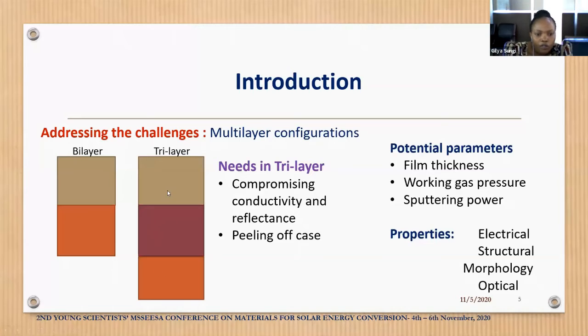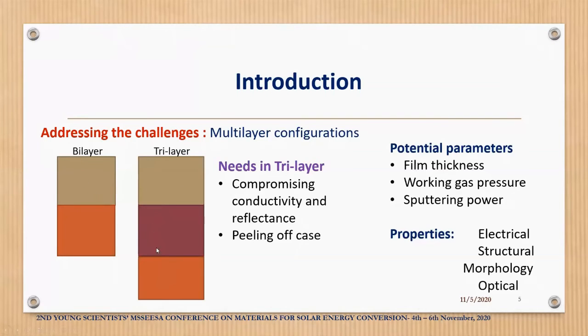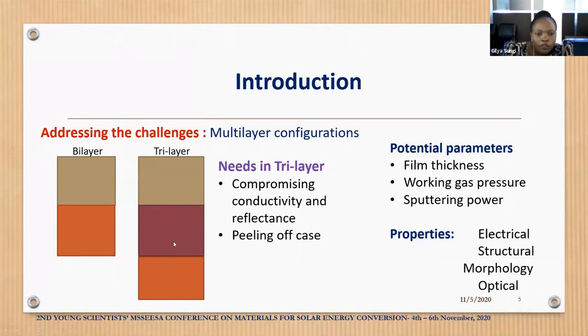Then tri-layers have been used recently, and a lot has been done in tri-layers, whereby other authors have been sandwiching molybdenum oxide in between a bilayer to get tri-layers, and others have been depositing tri-layers with the same deposition condition, but differentiating the deposition method, like RF and DC. But in this study, we are going to focus more on depositing tri-layers under different conditions, using direct current sputtering. So there is still a need in tri-layers to compromise the conductivity and reflectance and to solve the peeling off cases. So this study is based on compromising these parameters.